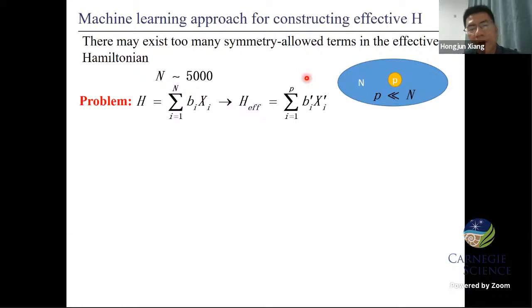So we can use group theory to obtain all kinds of complicated invariant terms. But we found that there may exist too many symmetry allowed terms in the effective Hamiltonian. For example, in a system with the spin degree of freedom and the atomic displacement degree of freedom, the number of terms could reach 5,000. If we have 5,000 terms, then we have 5,000 parameters. This is very hard to determine.